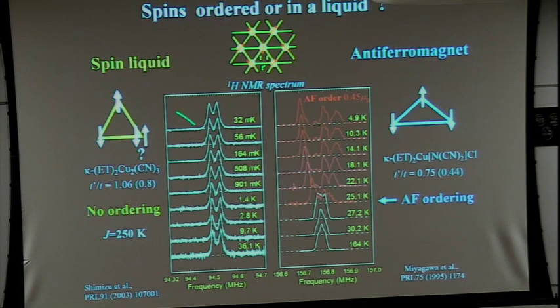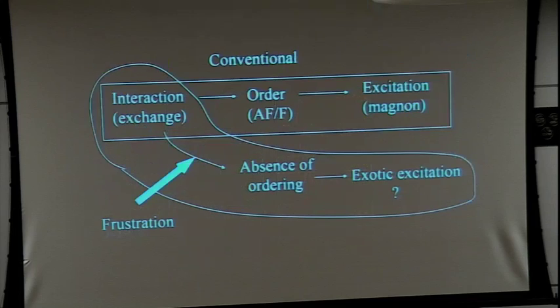However, the nearly isotropic triangular lattice does not show any clear splitting or change of NMR spectra at low temperatures. So this is unambiguous evidence of non-magnetic ordering, and very probably an indication of a spin liquid. In conventional many-body systems, the interaction among the ingredients leads to some kind of order. In spin systems, usually a ferromagnetic, antiferromagnetic, or spiral ordering state results, which is regarded as some classical order. And the excitation from the ground state is described by a particle in spin systems, the magnon.